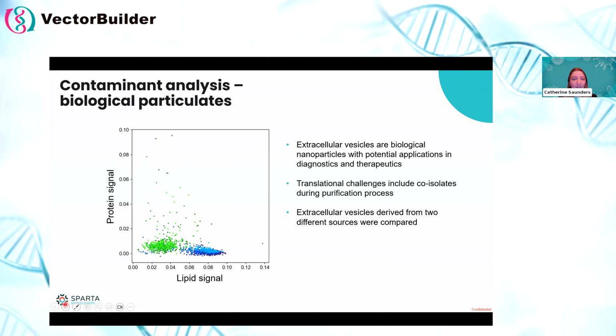However, one of the really key challenges with the translation of these EVs to the clinic is their purification. In particular, it's known that it's very challenging to separate these EVs from other biological nanoparticles of a similar size and density, known as lipoproteins, because these very commonly co-isolate with EVs during the most common purification methods. So what we have here with these EVs is a case of a very heterogeneous sample where it's really important to understand the different particle populations that are present. And so this is where it comes to the fore to use these single particle methods rather than relying on bulk analyses where you'd get one sample, one averaged result.